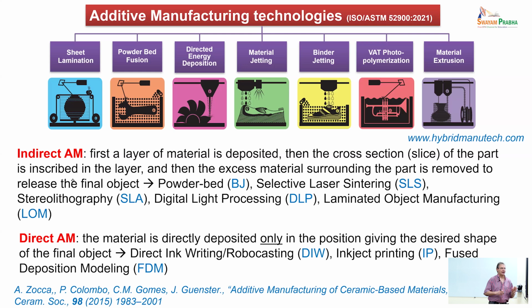And these include these technologies: direct ink writing, inkjet printing, or fused deposition modeling. While indirect additive manufacturing is an approach where you deposit a layer of your material, you inscribe a shape of that layer using different approaches, and then you remove the excess powder. And this means, for instance, that you cannot make an enclosed space, enclosed cell, because you would not be able to extract the unbound powder from that area. And these technologies include binder jetting, selective laser sintering, stereolithography, DLP, and laminated object manufacturing.